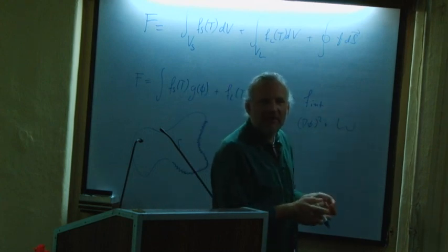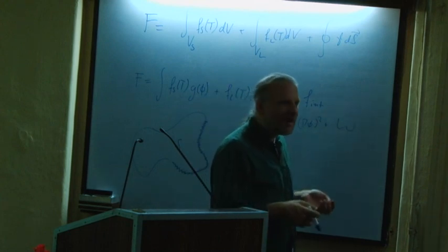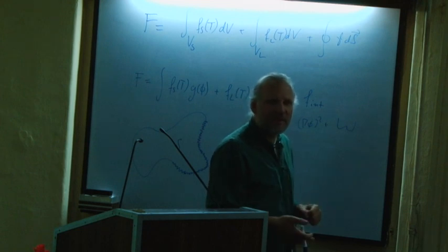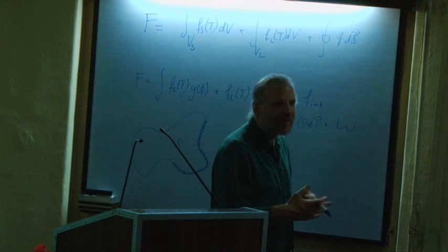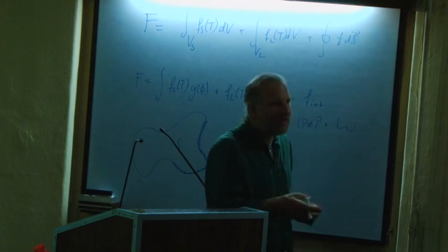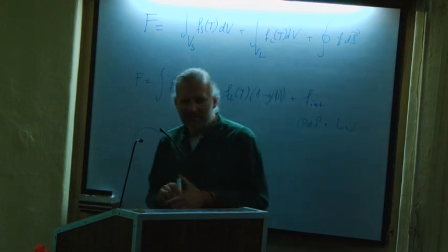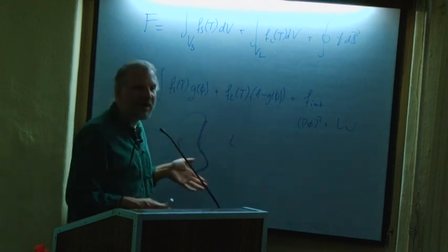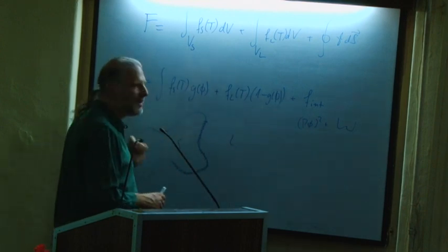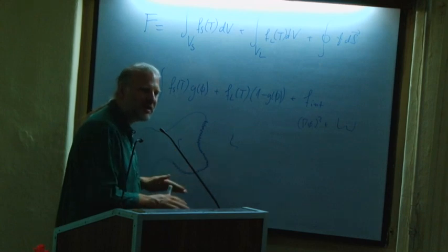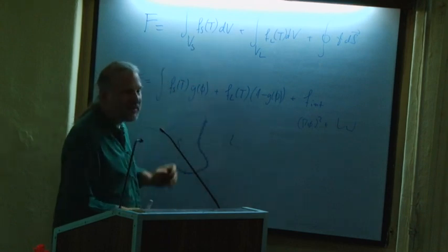And you can already guess that the approximation is more precise when the interface is thinner, because then you get closer to this infinitely sharp interface. Okay? And so that's this top-down spirit. I start from the infinitely sharp problem and I smooth it out by going to this phase field representation.